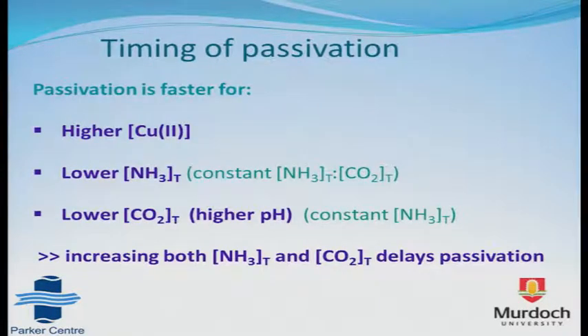This passivation has been found to take place faster for increasing copper concentrations and for lower ammonia and carbonate concentrations. So both the ammonia and the carbonate delay passivation.